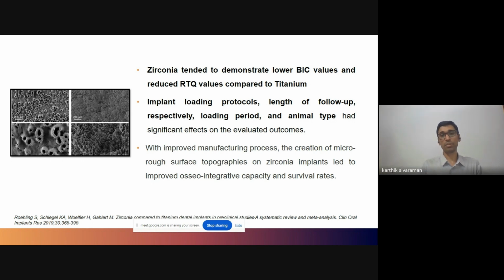For instance, when they compiled the studies, there were different animal models which had been used to compare zirconia and titanium. So it varied in the form of rats, pigs, you had dogs, sheep. So for instance, when they compared the performance of zirconia to titanium in pigs, there was a statistically significant difference in terms of performance. But when they correlated the results in a rabbit model, they found that both performed similarly. Normally, when we combine different animal models, it's always a source of controversy. But the authors did go ahead and combine these different animal models to come up with their final assessment that zirconia does demonstrate lower bone implant contact values and reduced removal torque